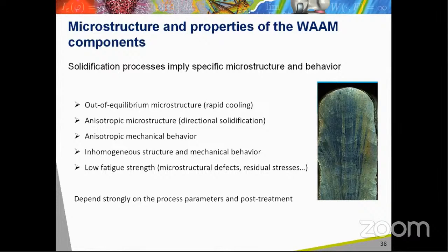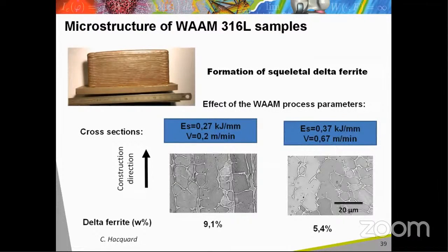Here is an example of microstructure obtained for a 316L stainless steel produced with the WAAM process. Due to the rapid solidification and cooling, a skeletal delta ferrite is formed in the austenite dendrites that can have a detrimental effect on the mechanical properties. The content of the delta ferrite depends on the process parameters, an increase of the energy produced by the increase of the arc power producing a significant decrease of the ferrite content.